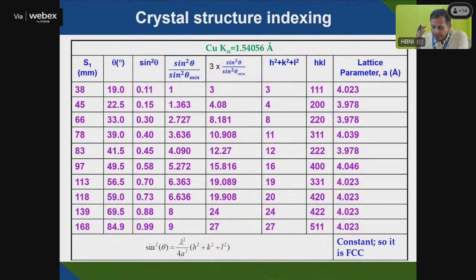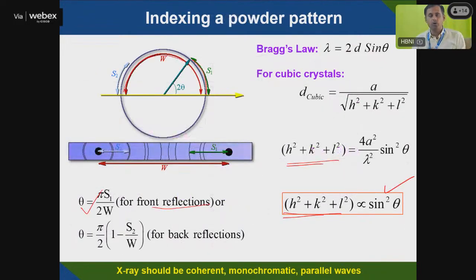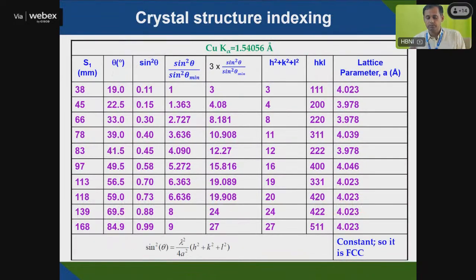As I discussed, if you identify a crystal structure, for example, you got an X-ray pattern, and from the X-ray pattern you now identify whether it is an FCC structure, a BCC structure, or a simple cubic structure. For that, you have to use that h square plus k square plus l square, the extinction rule, and see how it's following.